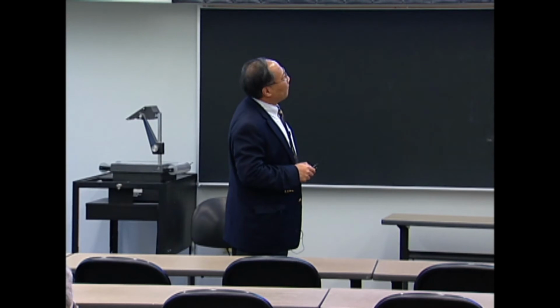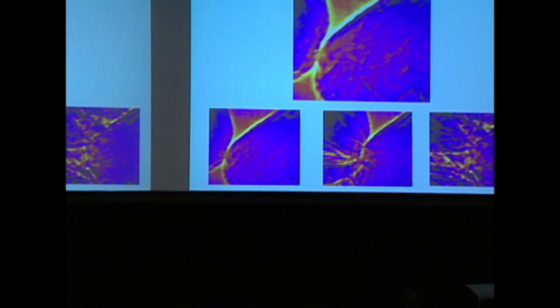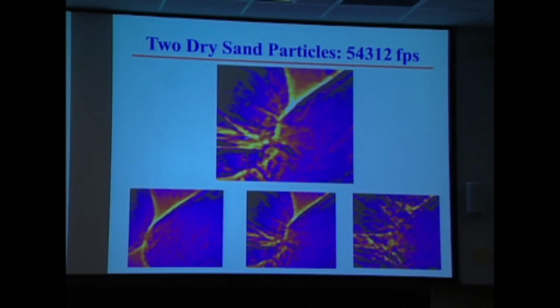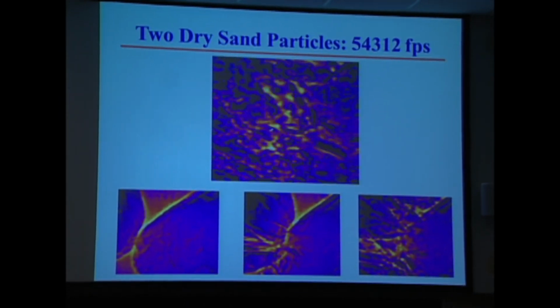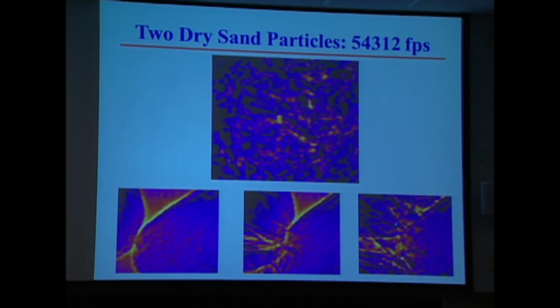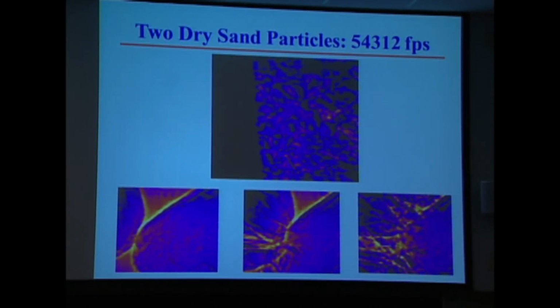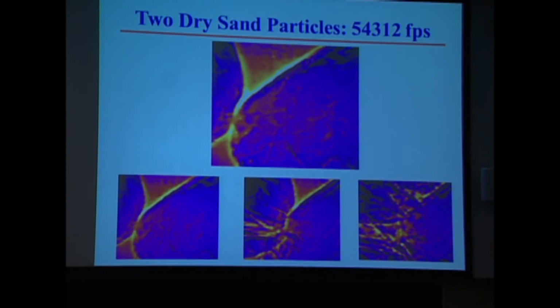So here, 2 sand grains get pushed horizontally, and you're going to see surface damage. The image you're shown is just through the thickness. So on the surface, you see the initial surface damage, and the one side developed damage much faster. Eventually, this side explodes, but on the other side, you see the damage stop. So if 2 sand grains are against each other, when they fail, one would explode, and the other one will survive.